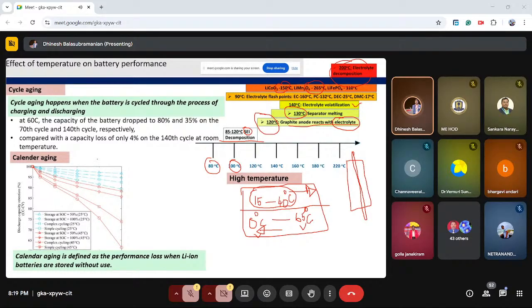So for an example, let us assume when you charge your battery and discharge your battery at 60 degrees Celsius, the capacity of the battery drops to 80 percentage and 35 percentage on the 70th cycle and 140th cycle respectively, compared with the capacity loss of only 4 percentage on the 140 cycles at room temperature. So when you operate at 20 degrees Celsius or 30 degrees Celsius, only 4 percentage of drop happens after 150 or 200 cycles. But you should not move above the extended limit of 60 or even above, and even 60 is considered a highly alarming situation where you need to work on the cooling of your battery.